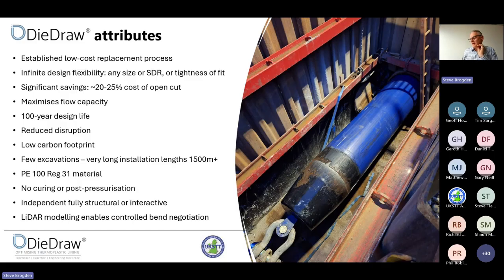Significant savings. I'll put an approximate figure on this, and I'm being a bit conservative, but we believe we're about 20% of the cost of open cut. So I've said 20 to 25% of the cost of open cut. And I was a bit surprised about this, but on the case studies I've seen recently, we seem to be lower cost overall than cured in place linings, particularly because we can pull very long installation lengths in one go.